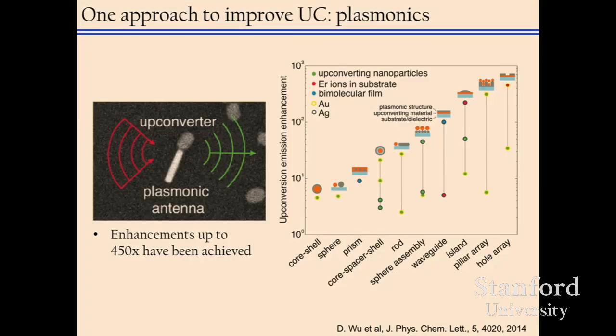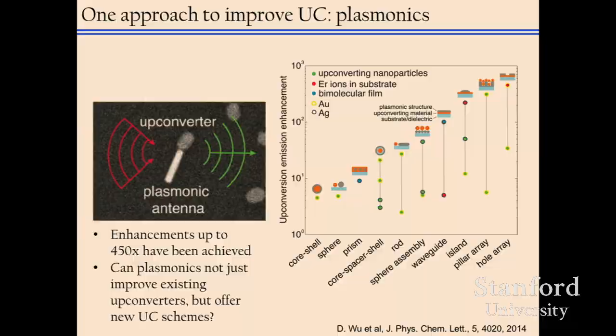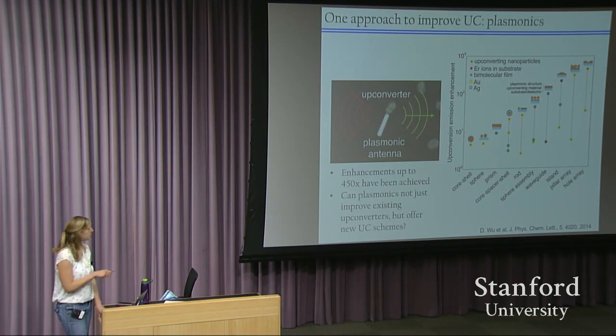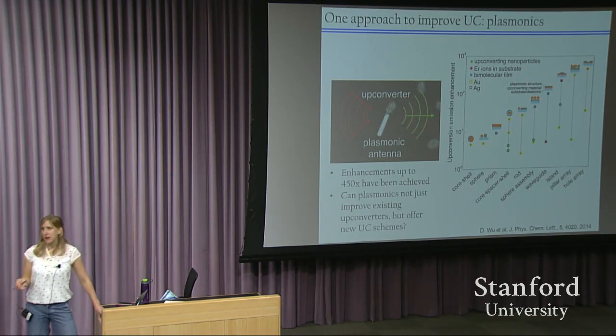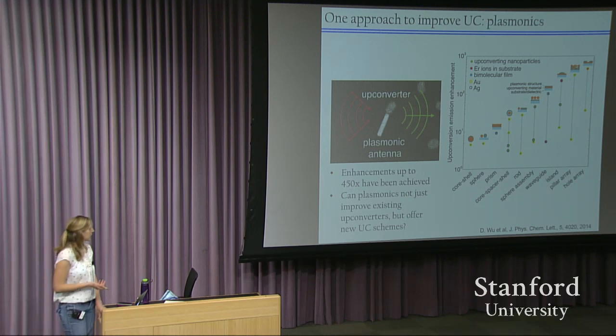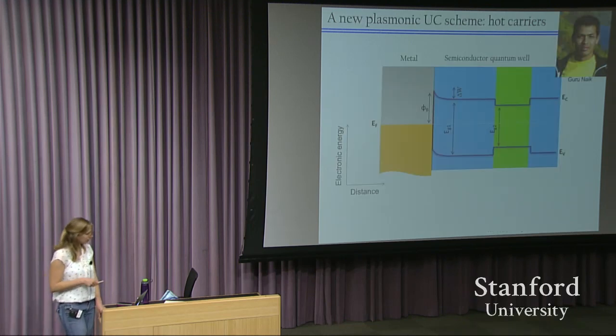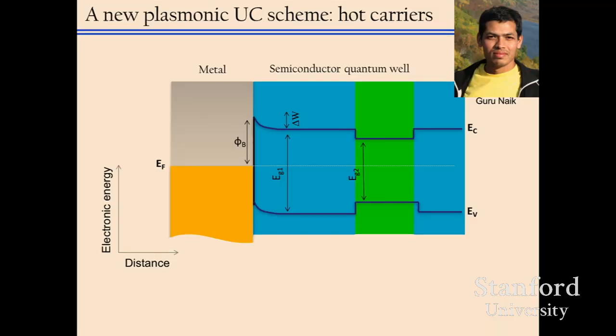So what my group has done is worked on a new scheme for upconversion. And it's based on some insights from plasmonics, where we have these metals that can act as nano antennas. And historically, what people have done is put metal nanoparticles near an upconverter to more efficiently funnel light into the upconverter and then get the higher energy light out of the upconverter. But what we wanted to do is not just use plasmonics to enhance these sorts of light-matter interactions, but enable new upconversion schemes. So here's a layout of the upconversion scheme.